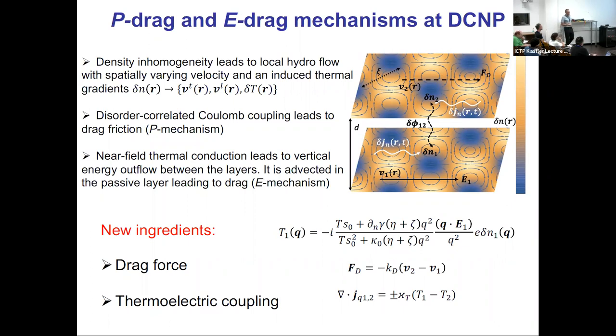So the situation is the following. We learned in a single layer case that when I drive the system, even electrically, I necessarily develop temperature gradients. These temperature gradients would be transported to the other layer as well. So there will be induced temperature gradients in the other layer as well. That would give, in Levitov's terminology, a vertical heat flux from one layer to the other layer. And so this would be the E drag mechanism. And the P drag mechanism, because of the disorder correlations, is the usual Coulomb-mediated electron-electron scattering between the layers.